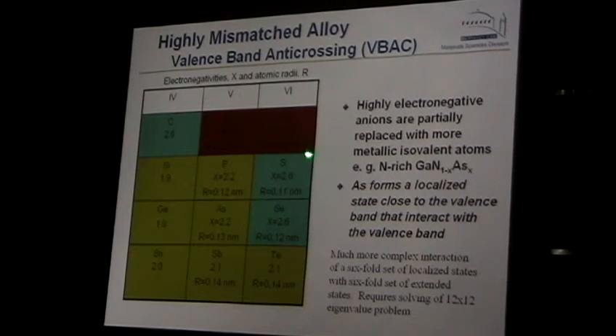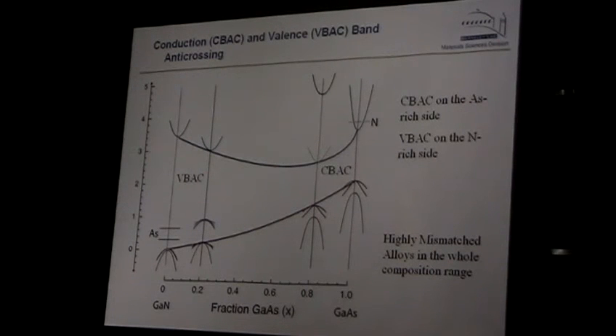However, the question was, what could we do the opposite? We take gallium nitride, it has nitrogen, and we replace some of the nitrogen with arsenic. We go from the other side, right? Or take, let's say, zinc oxide and replace some of the oxygen with sulfur or selenium. So there are a lot of combinations which were never realized. And so what's happening is quite interesting. This is a cartoonish version of quite an interesting phenomenon.